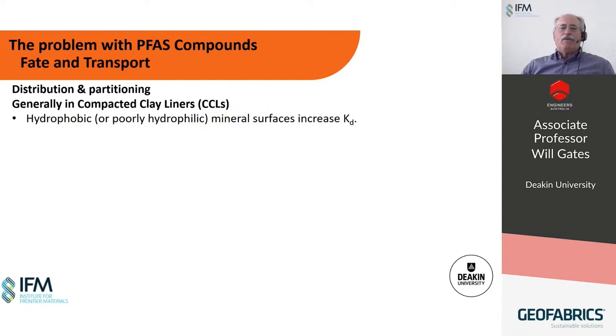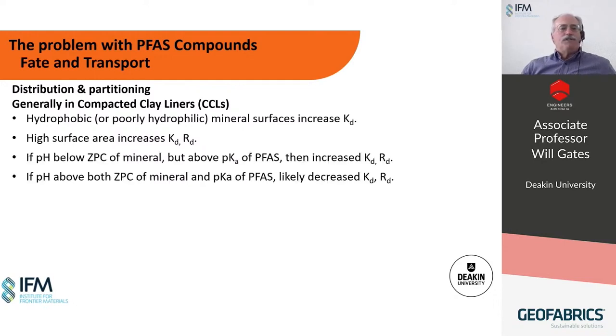So to recap, the physical and chemical properties of mineral surfaces impact the adsorption and thus the fate and transport of the PFAS. If they're hydrophobic or poorly hydrophilic, or if they have a high surface area, we can expect that the distribution coefficient will go towards the mineral surface, and that will then result in retardation. If the pH of the solution or the leachate is below the point of zero charge of the mineral, then we can expect that the PFAS is going to be adsorbed if its pKa is low. If the pKa is high, then we can expect that adsorption onto the mineral surface will be lower.